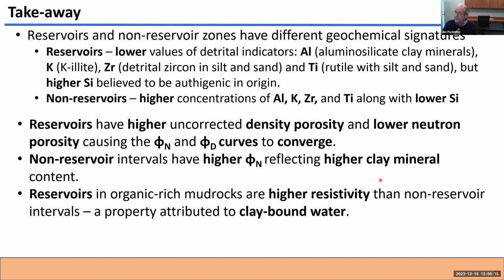So reservoirs, from what we've observed, can have higher uncorrected density porosity and lower neutron porosity because of that lower clay content, causing the neutron and uncorrected density curves to converge. In contrast, our non-reservoirs have high neutron porosity. It separates from the density porosity because of that high clay content. And I think this is important: the higher resistivity in those reservoirs, I think that's an important characteristic.